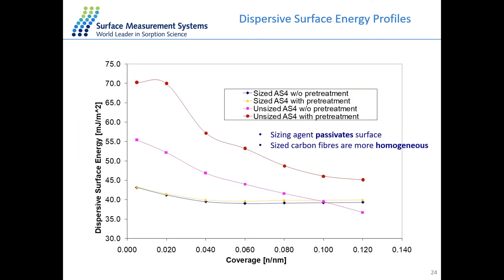So here's the result of four different carbon fibers. As you can see, the red line and the pink line for the unsized carbon fiber are much higher in surface energy, and they vary a lot with the surface coverage. It has both high energy sites and low energy sites. That means the unsized carbon fiber is very heterogeneous in nature.